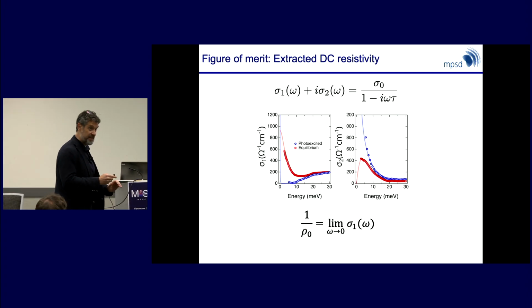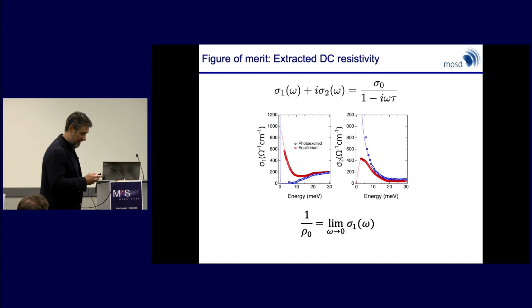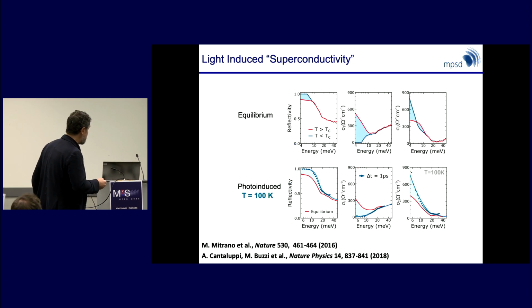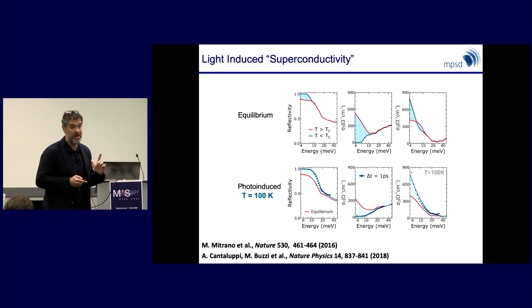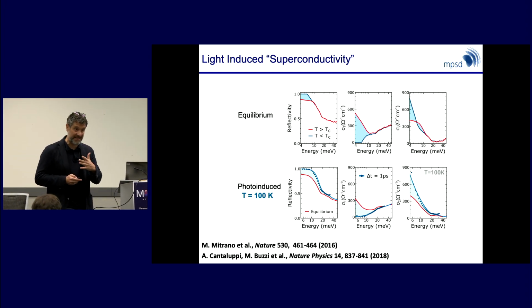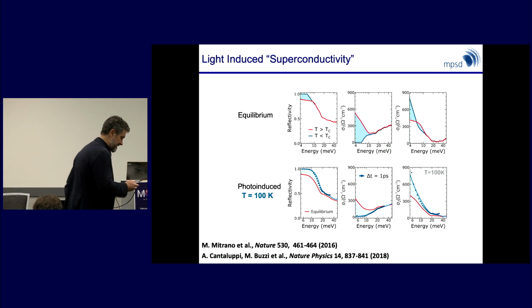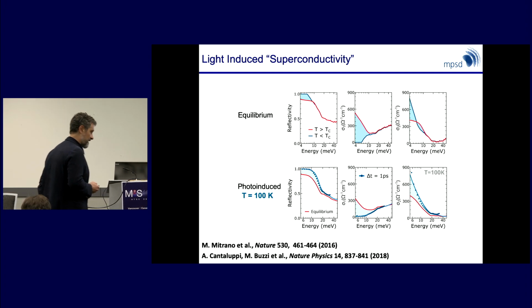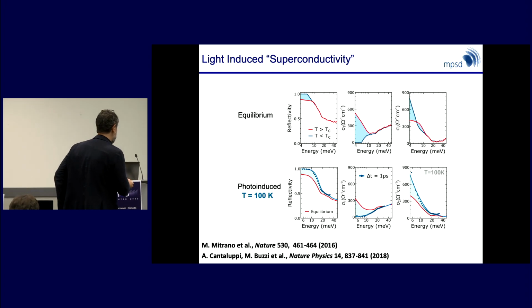Okay, so this is all that was good. I'm going to use in the next part of the talk one particular figure of merit. I'm not going to keep on showing you all these 3 optical properties. I'm going to take these spectra and I'm going to fit them with a Drude model. The advantage of the Drude model is that it can both fit without a gap. The Drude model can both fit a metal with a finite scattering rate and a superconductor with infinite scattering time, 0 scattering rate.